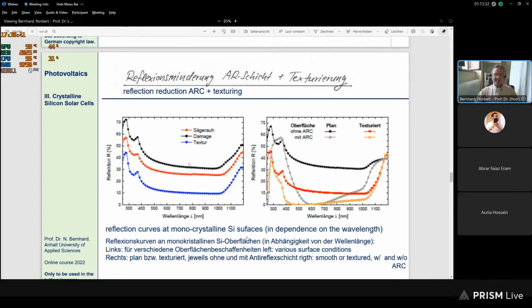In the left picture, the red one would be as the wafer comes after sawing. That means, we have said saw damage removal, then the reflectivity has even increased, but after texturing, this blue curve, it has been reduced. This is texturing alone. On the right-hand side, we see how the texturing with the anti-reflective coating together performs. The black is just the anti-reflective coating.